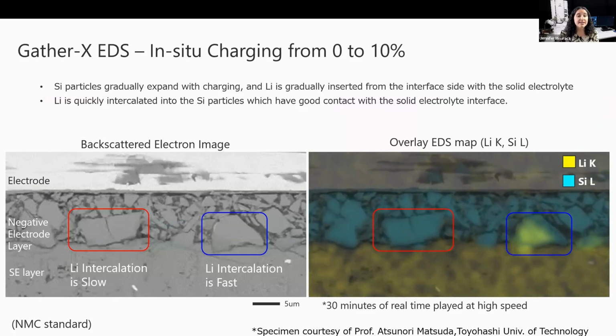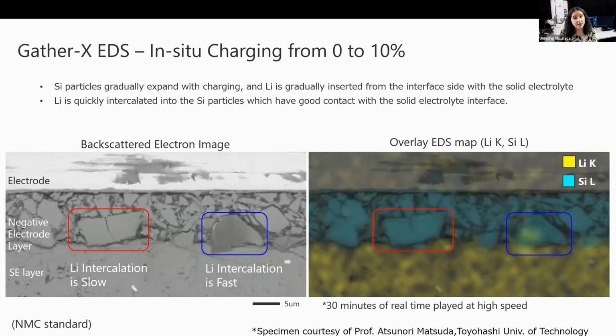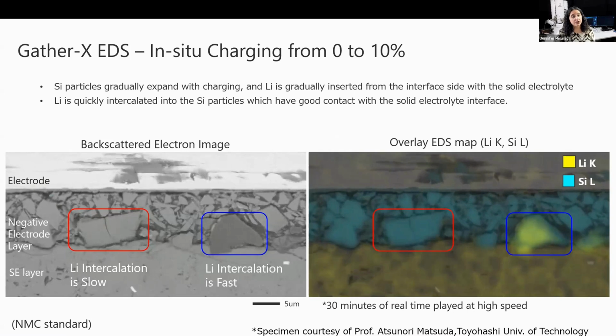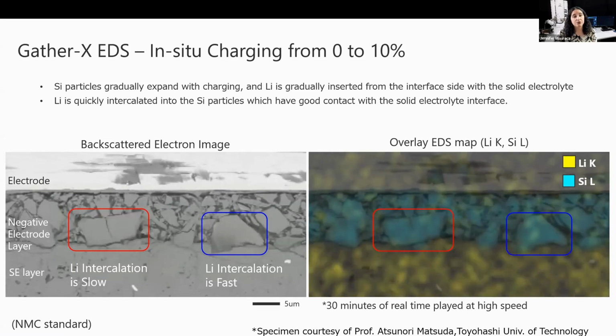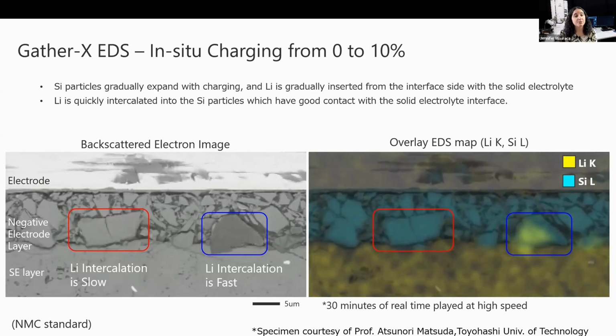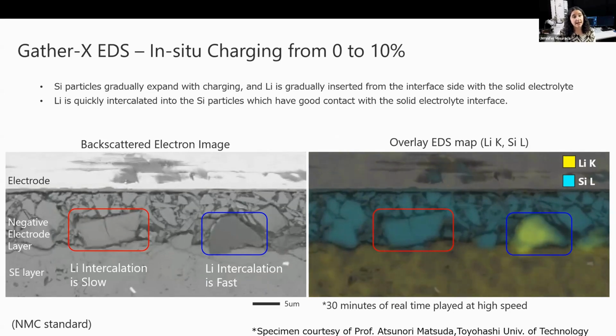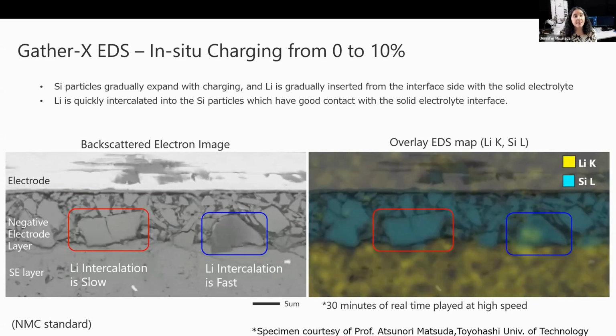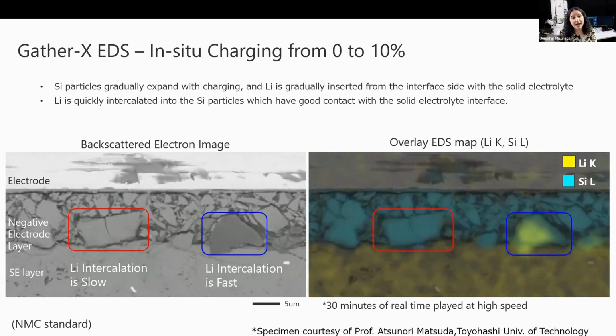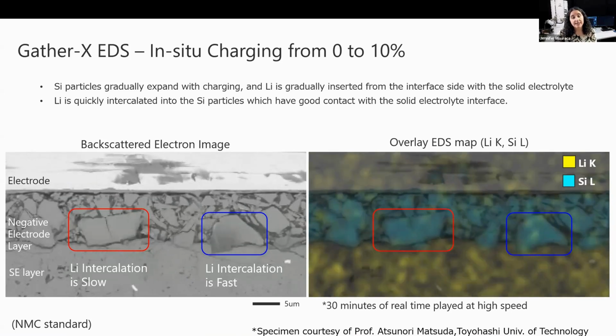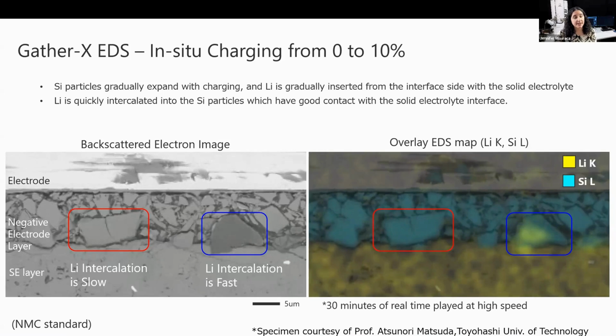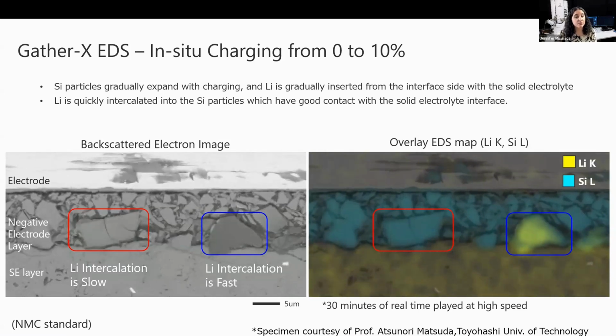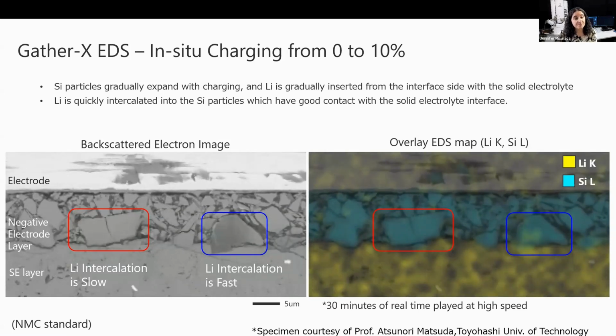Okay, so this is how the silicon negative electrode changes during charging of an all solid state battery. The charging in this slide is from 0% to 10%, and the actual elapsed time is 30 minutes. The left image is a backscattered electron image, and the right is an EDS map using the Gather-X detector with lithium K in yellow and silicon L in light blue.